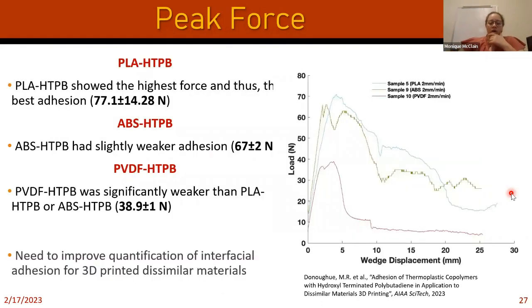So here I have some representative curves of this test. Essentially, we're loading the wedge between those two layers, and the force increases until something starts occurring. So it either is debonding or maybe it's tearing or something like that. We still need to refine this process a bit to make sure we're looking at the right mode. But in general, we can see some differences here. So there are some improvements to be made.